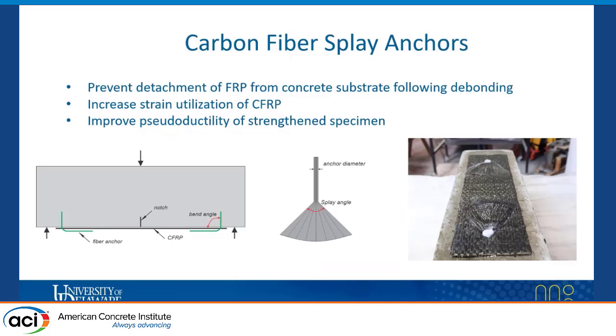Due to the adhesive failure leading to debonding, there's a need to include some form of anchorage, such as carbon fiber splay anchors, to mitigate this detachment of the FRP after debonding initiates. If you're not familiar with carbon fiber splay anchors, they consist of two main components: the first being the anchor dowel, which is what is embedded into the concrete, and the second being the anchor splay, which is what is fanned out over the CFRP and does the anchoring.